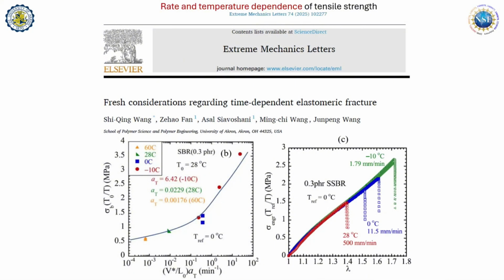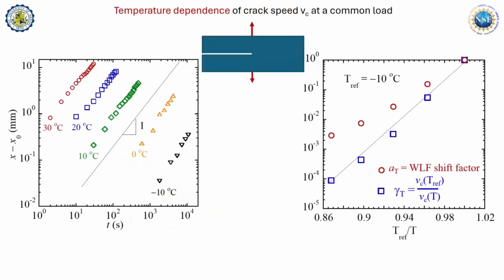So let me match the WLF. In other words, at lower temperature, I'm going to stretch slower. At higher temperature, I'm going to stretch faster. So if WLF holds, then they should fracture at the same strength. But it doesn't. These are matched, but it doesn't. So now, guided by this, you can start to go a little deeper.